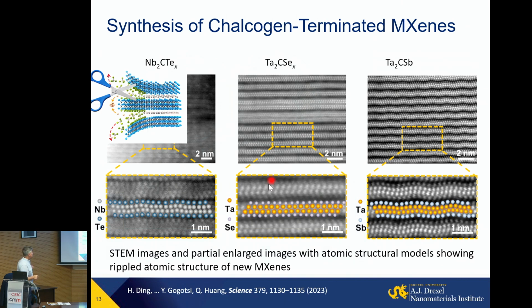But for us, what is important, we can create new materials with very different properties. For example, what you see here are materials which some of you may look at like dichalcogenide because there is tellurium or selenium on the surface. But in the middle, instead of a monatomic layer of transition metal, we have a layer of carbide. It's like a carbochalcogenide, a hybrid between dichalcogenide, because the surface looks like the surface of dichalcogenide, and in the middle you have a metal carbide. Or for the first time we put antimony. This was the first publication, antimony on the surface.